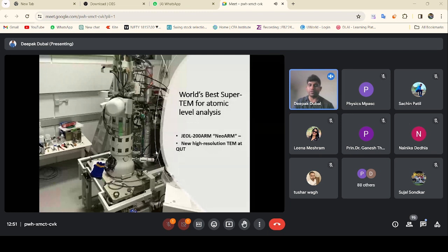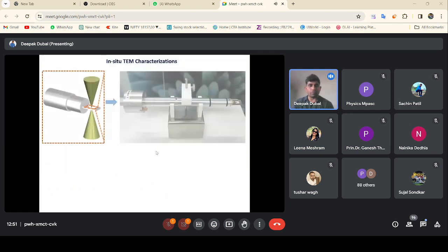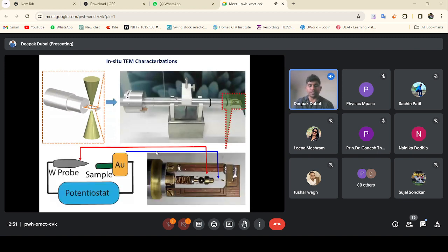So we recently got this super transmission electron machine where we do a lot of in situ characterization. So what we did is we modified the TEM holder. You can see the schematic here. We have this gold current collector, we apply the sample here, and we have the tungsten here, where we apply the lithium, and we put everything into the TEM machine, and then through the potentiostat, we apply voltage. And then we see how the material works.